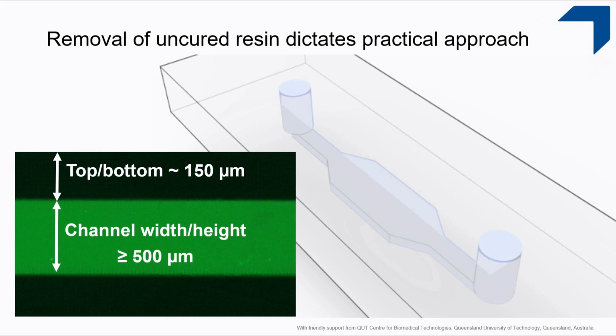Now, this may sound strange, but it is a very difficult situation. What you see here is a cell, one of these microfluidic cells. And you see on the green and black part here the dimensions of this. So top to bottom, maybe 150 microns. That's 1.5 hairs width, or 500 microns, 5 hairs width. That's not much. And when you DLP print these systems, then you're printing from a resin. And that resin is entrapped in these volumes that you want to do the reactions in.